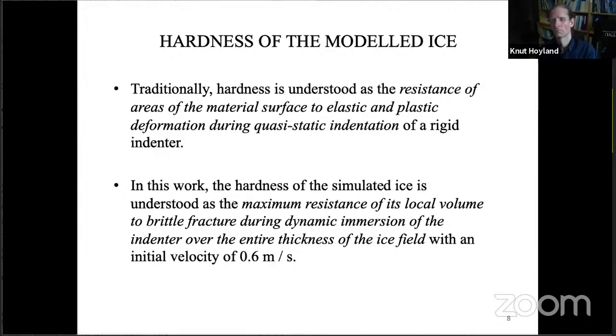To achieve better understanding, the authors suggest refining the term hardness. In addition to resistance of the area of the material surface to elastic and plastic deformation during quasi-static indentation, they suggest using the maximum resistance of its local volume to brittle fracture during dynamic immersion of the indenter over the entire thickness of the ice field.